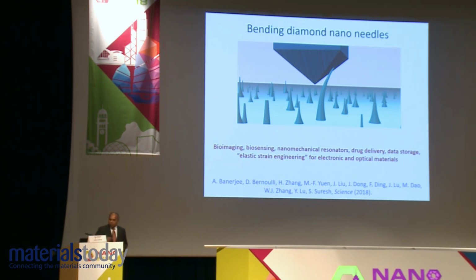So colleagues at the City University of Hong Kong, here the names are listed here, Professor Zhang and his co-workers have been working on nano diamond for quite some time. So if you take a silicon substrate and deposit a thin film of diamond on top of it through plasma-enhanced chemical vapor deposition, and then you use etching to create needles where the height of the needles is of the order of 200 or 300 nanometers, and the diameter is probably less than 100 nanometers, you create many of these diamonds on a substrate.